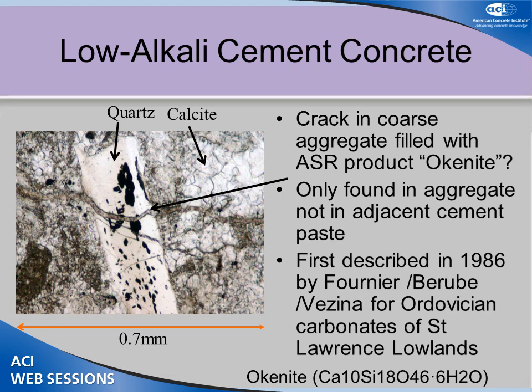Chris did some optical petrography on this, and we found evidence of fracturing in the aggregate. This is a quartz grain in the limestone, and you can see a fracture through it. You can see the gel in here, and he identified this as okenite, which has this formula. It's a calcium silicate hydrate, which has been found in some other work described by Fournier and Bérubé on the Quebec side, with similar findings in some of the gel that is crystallized to some extent.